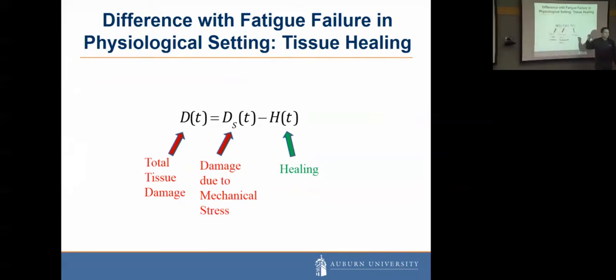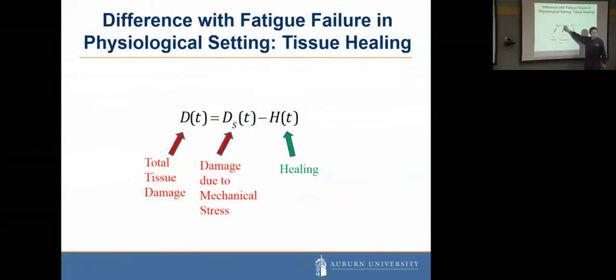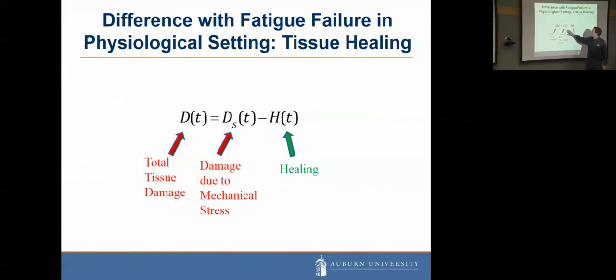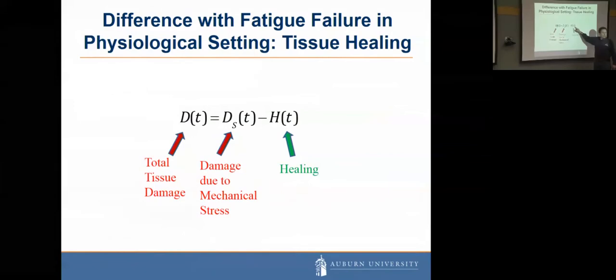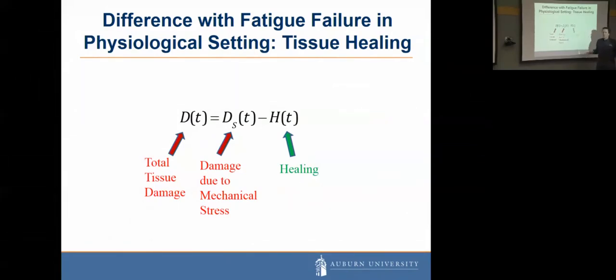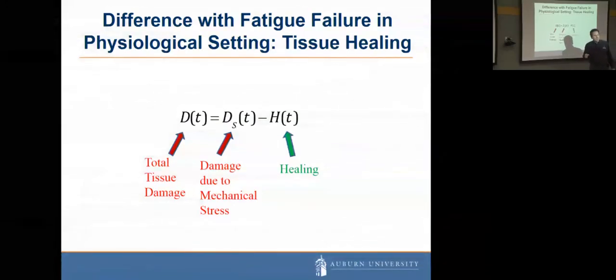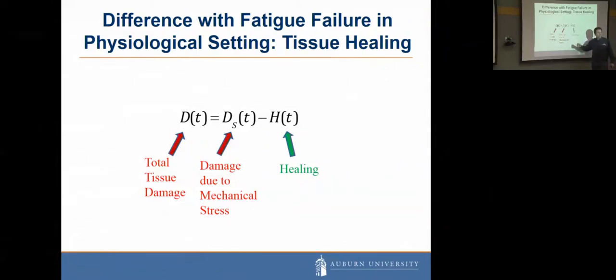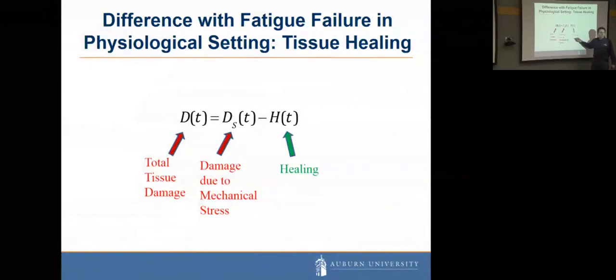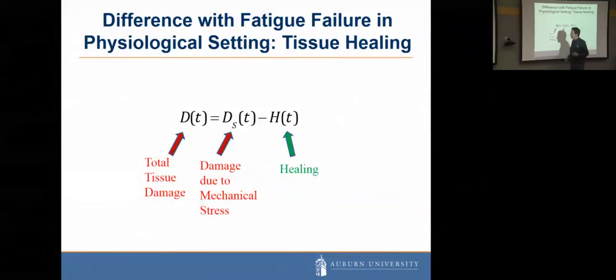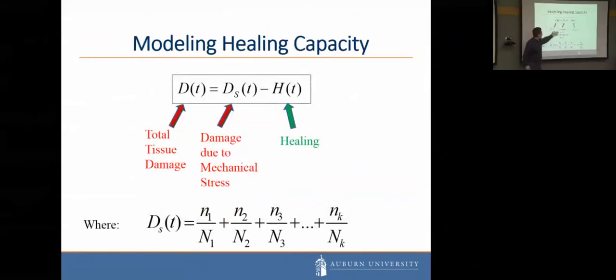And he had two versions of it. One was that the total tissue damage is going to be equal to the damage due to stress, which is that fatigue failure Palmgren-Miner example that I showed. And then he also included damage due to aging and damage due to disease, and then minus the healing that can occur at the tissue. So if you're talking about a time that's fairly limited in scope, aging isn't going to be a big issue, and we'll say disease is not a big issue. So you can boil this down to the total amount of tissue damage being equal to the damage due to the mechanical stress minus whatever healing can take place. And this damage due to mechanical stress is the sum of the Palmgren-Miner equation.